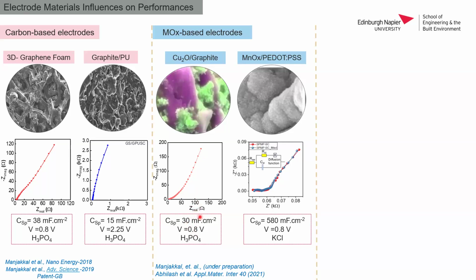I also used other electrolytes here, such as sodium chloride, NaPF6, and calcium chloride. Depending on the type of electrolyte, I noticed that the performance of the device is varying. In another metal oxide, which I did along with my colleague, a metal oxide with PEDOT:PSS in a stretchable version of a supercapacitor, I found very high performance. This is due to the method of fabrication we are using here.